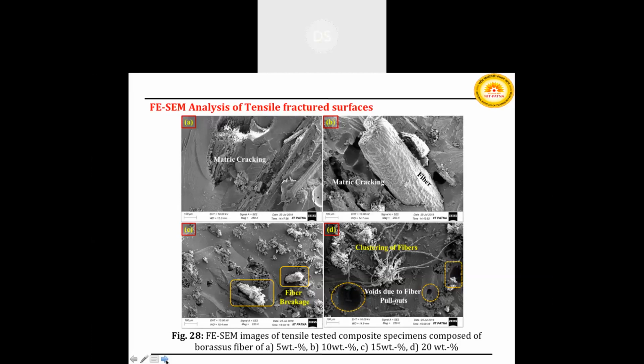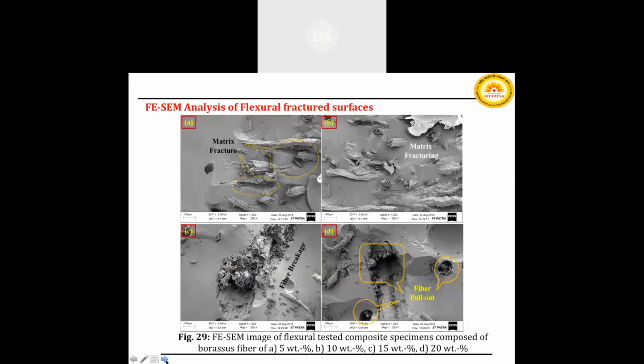This FESEM analysis of fracture surface of flexural test specimen. In this test, matrix breakage, fiber breakage, and fiber matrix debonding were observed. If Borassus fruit fiber weight percentage increases, voids were made due to the fiber pull out because of weak adhesion between the